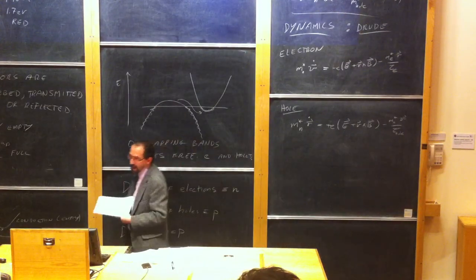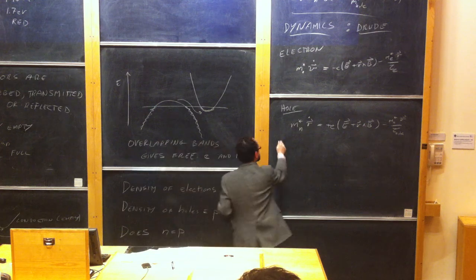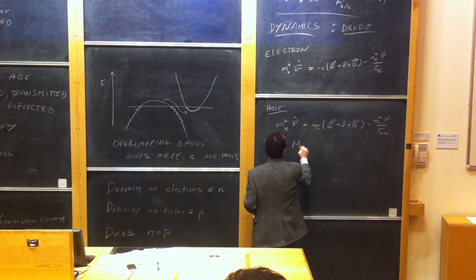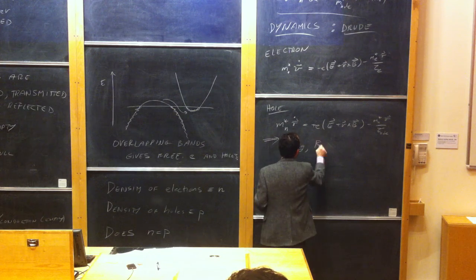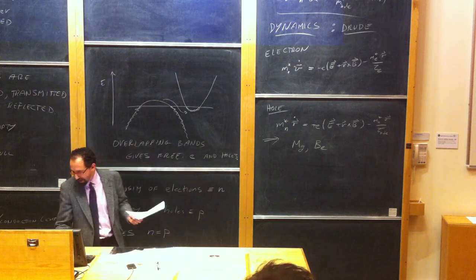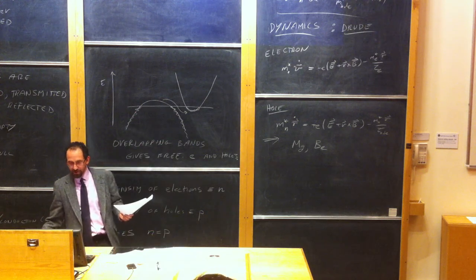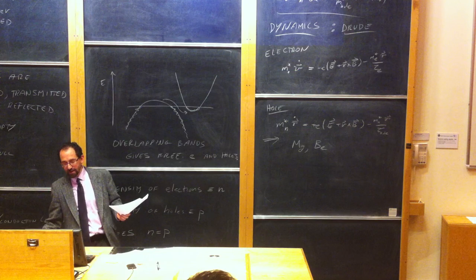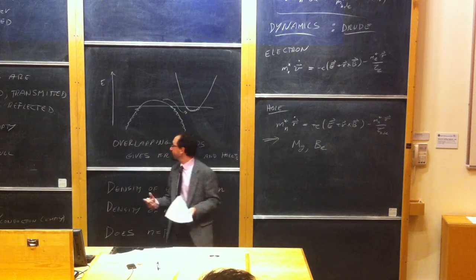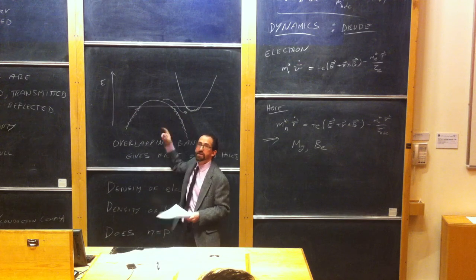Well, the cases where the Hall coefficient came out with the wrong sign were magnesium and beryllium, which have 2 electrons per unit cell. Actually, I can go back up to these two. They both have 2 electrons per atom. They're divalent, and you would think that it would be a filled band, but it's not a filled band because the bands overlap. It's just like calcium.